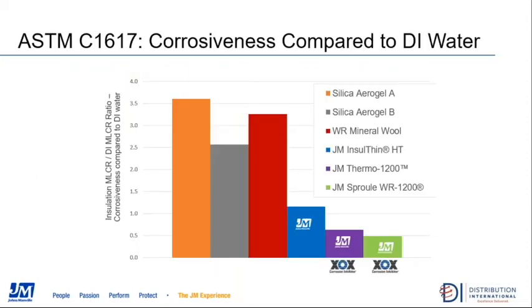This chart represents the results of testing performed by a third-party lab comparing the mass loss corrosion rate results for different insulation materials as compared to that of DI water. DI water is typically considered pretty inert, free of contaminants that might accelerate any type of corrosion, and so that is the baseline. The corrosion rates represented by the different colored bars on the chart are that ratio of the mass loss corrosion rate for the individual insulation material divided by the mass loss corrosion rate for DI water conducted as a benchmark or a baseline during each of these individual tests.